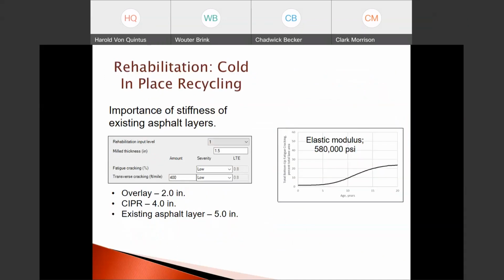This now shows the importance of the existing layer, the condition of the existing layers. And we included these just to show if we have a good intact or good asphalt layer versus a relatively poor condition asphalt layer, what impact does that make on reflection cracks? And so what we've shown here is an elastic average back calculated layer modulus of 580,000. This is for total bottom up fatigue cracking. And you can see we have about 20% cracks, bottom up cracks that are going to reflect through over a 20-year design. And so that's about 580 KSI.